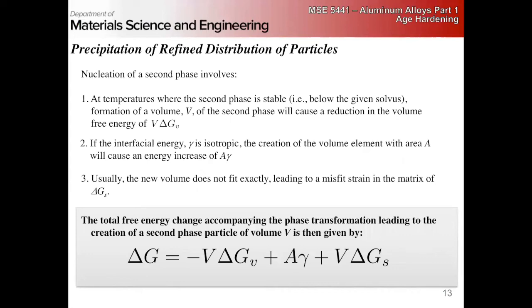In real cases, we have to worry about the interfacial energy, right? How difficult is it? How likely are these two phases to want to be near each other, right? If the interfacial energy is low, we can have lots and lots and lots of small regions. If the interfacial energy is really high, the system will tend to minimize the interfacial component by nucleating and growing large particles that are well separated, right?